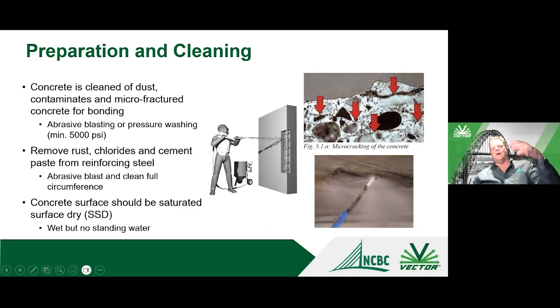So if you're going to rely on the repair material to bond very well to the substrate, you need to have the sound substrate. So be able to come back with a final abrasive blasting or higher pressure water blasting, just to remove these loose pieces and make sure that you have a nice sound concrete surface for the repair material. And then most techniques would require a surface saturated but dry surface. So basically you want to have a fairly wet concrete, but not with any puddling on the surface, to prevent a lot of moisture being pulled out from the repair material into the substrate.